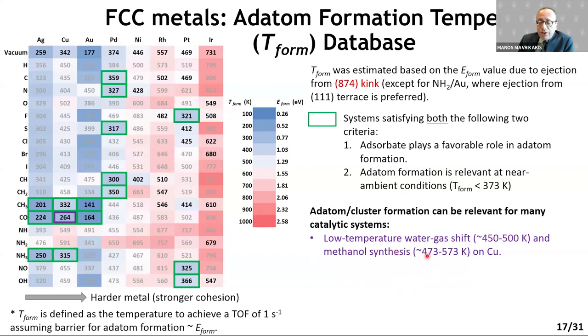Similarly, methanol synthesis is catalyzed by copper. Reactants are CO, CO2, and hydrogen, taking place at several tens of atmospheres, a high pressure reaction, at 500 degrees Kelvin and above. Imagine, this reaction consumes 2 to 3% of all energy produced on the planet on an annual basis. If you can understand the reaction mechanism and find a new catalyst that decreases the temperature at which this reaction needs to be run, you can save a tremendous amount of energy production, which goes hand in hand with polluting the environment.